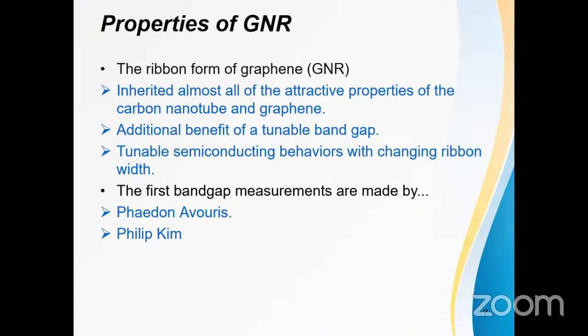Various properties of graphene nanoribbons. It is a ribbon form of graphene, and it inherited almost all the attractive properties of carbon nanotubes and graphene, like high mobility and high electrical and thermal conductivity. It has the additional benefit of a tunable band gap, that is, its band gap can be adjusted by applying external voltage. Tunable semiconducting behavior with changing ribbon width. The first band gap measurements were made by Phaedon Avouris and Philip Kim. Phaedon Avouris gave the theory of high on-off current ratio and large transport band gap at room temperature, and according to Philip Kim, the energy gap scales inversely with the ribbon width.